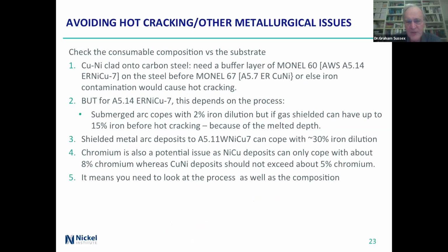If you're welding copper nickel onto carbon steel, you'll need a buffer layer of AWS A5.14 ERNiCu-7, on the steel before you put down the next layer of the Monel. And Monel is just the high alloy, the copper nickel. Or else the iron contamination will give you hot cracking. But if you're talking about the A5.14 ERNiCu-7, it's going to depend on the process. With submerged arc, 2% iron dilution, but if it's gas shielded, it can have up to 15% before you get hot cracking. My understanding is it's because of the melt depth and how far down you're actually pulling up the metal to be contaminated.